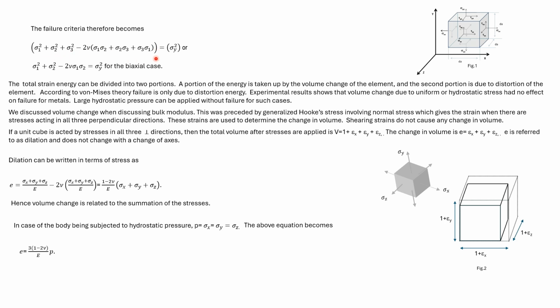This failure criteria is in 3 dimensions. If we have sigma 3 as 0, then we get this equation which is for the biaxial case. These are the stresses that will act on an element. Generally, the total energy of the element can be divided into 2 portions. One portion of the energy of the element is taken up by volume change of the element. The second portion of the energy is taken up by distortion.